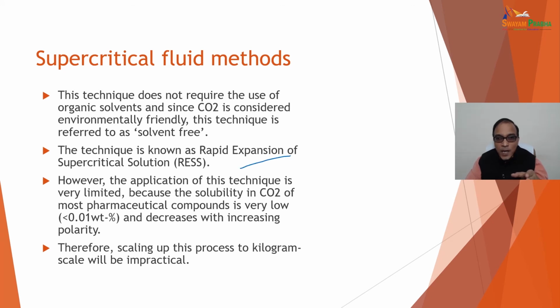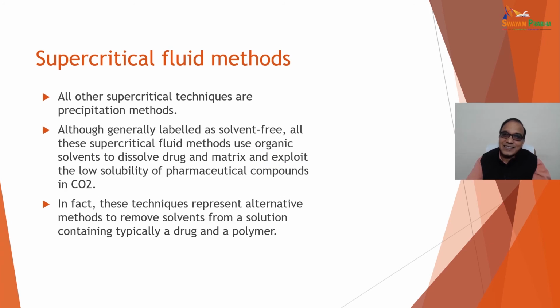Okay, RESS. However, the application of this technique is very limited because the solubility in CO2 of most pharmaceutical compounds is very low, less than 0.01 weight percent, and decreases with increasing polarity. So that's why it's of limited use for pharmaceutical purposes, but yes, it is one of the most advanced methods nowadays. Therefore, scaling up this process to kilogram scale will be impractical. All other supercritical fluid techniques are precipitation methods. Although generally labeled as solvent free, all the supercritical fluid methods use organic solvents to dissolve drug and matrix and exploit the low solubility of pharmaceutical compounds in carbon dioxide. In fact, these techniques represent alternative methods to remove the solvents from a solution containing typically a drug and the polymer.